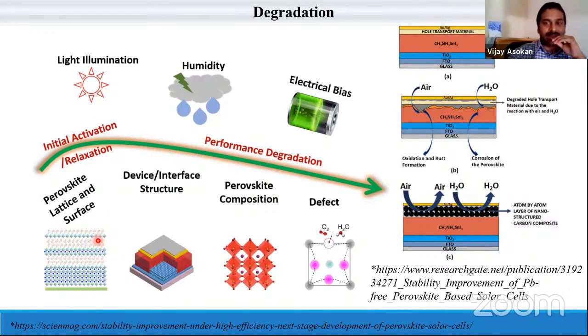Of course, in addition, there are many degradation factors, like the perovskite lattice and surfaces, that's intrinsic, which can be rectified by using different chemical or material combinations. Device interface structures also need to be considered. That's more important here. For example, air and water degrade the hole transport layer, which makes a degraded point, leading to rust formation and corrosion of the perovskite layer, since the degradation spreads from the hole transport layer toward the perovskite, as it is nearby in the device structure.